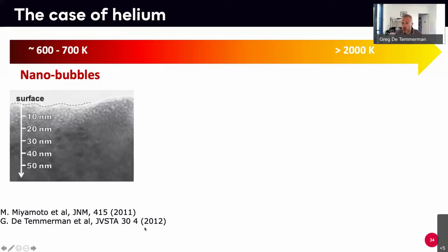And when it does that, the next helium atom will do the same thing, come at the same place, and so on. They start aggregating. When the helium cluster is big enough, it starts pulling tungsten atoms out of the lattice, creating self-interstitials and growing bubbles inside. So when you have helium in tungsten at low temperature, what you tend to see are nanoscopic bubbles, typically a few nanometers in diameter, created close to the surface.